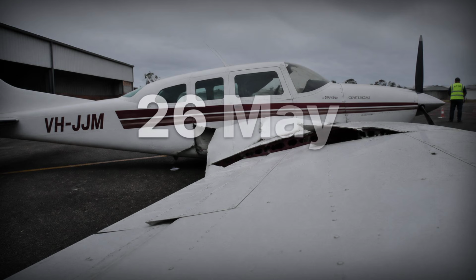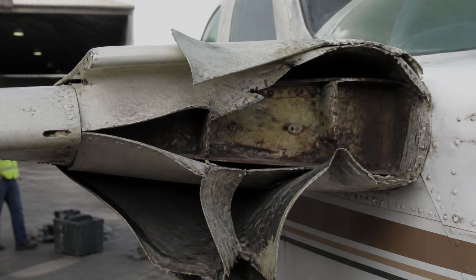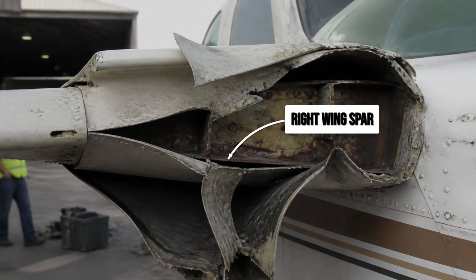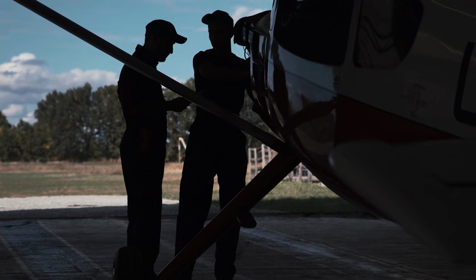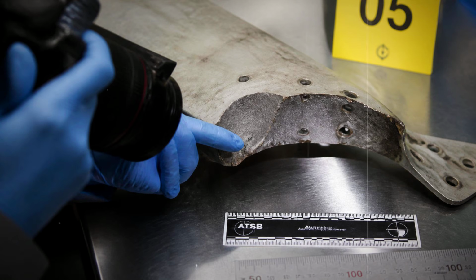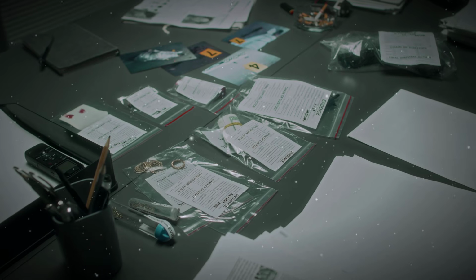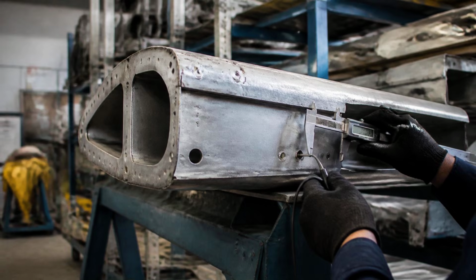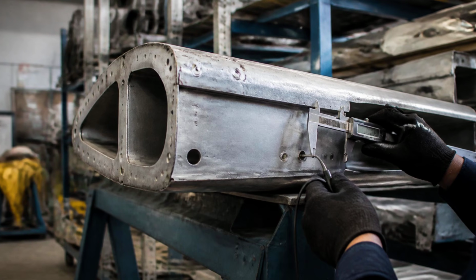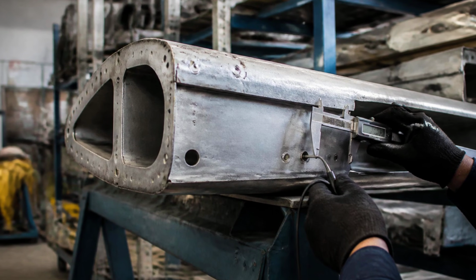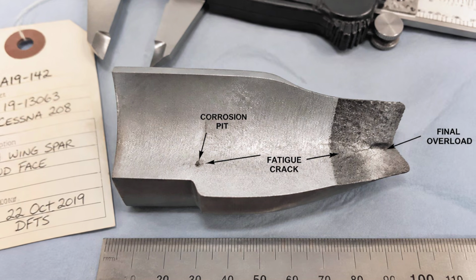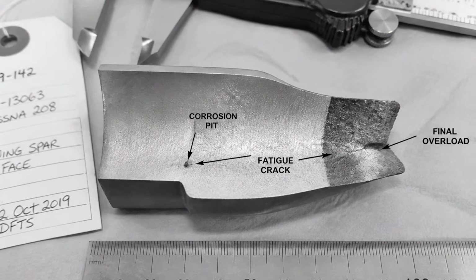On May 26, 2019, the right wing of a Cessna T210M separated during a low-altitude aerial survey flight in Australia. The Australian Transport Safety Bureau examined the fracture surface. They found fatigue cracking that had started at a corrosion pit measuring 0.011 inches deep, roughly the thickness of 2 sheets of printer paper. A pit that small, in a single load path forged aluminum structure with no secondary load path, grew a crack that propagated until the structure could no longer carry the load.